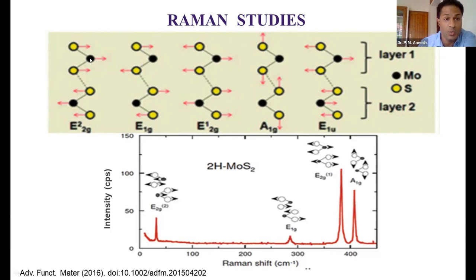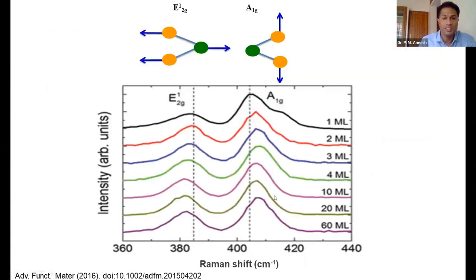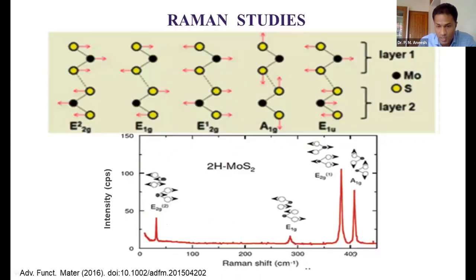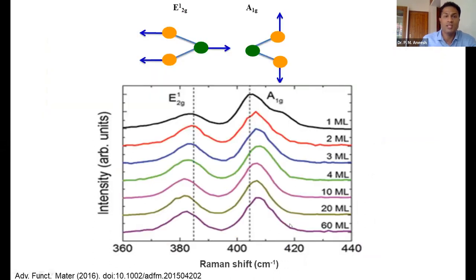So here it is the molybdenum atom and the yellow color represents the sulfur atom. These will vibrate in different ways. Depending upon the different vibrations, we have different modes of vibration. This is the typical Raman spectra of molybdenum disulfide, and you can see the different vibrations. But here we are mainly considering these two particular peaks, around 380 and 400.